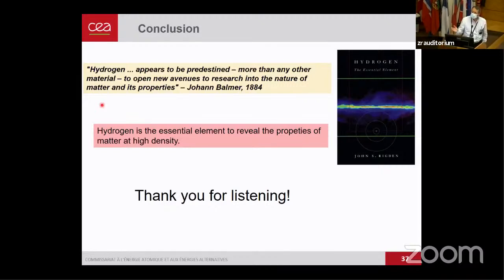Because the measurements when you go down are exactly reproducible. We show exactly the same spectra, so there is no change of the diamond. And then we say, okay, it could be a property of the diamond, but doing deuterium at much higher pressure, we show that we measure hydrogen before, and so it's not coming from the diamond. So there are two facts: it's completely reversible and the diamond doesn't change at all. We recover a perfect single crystal diamond, not attacked, and the measurements are reversible going down. And the fact that we measure deuterium at much higher pressure than the hydrogen shift means that what we're measuring on hydrogen is really due to hydrogen.